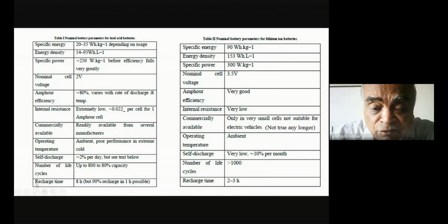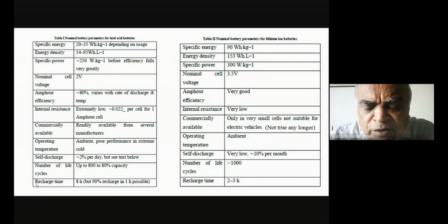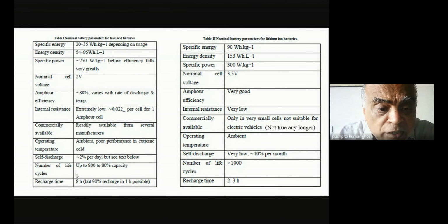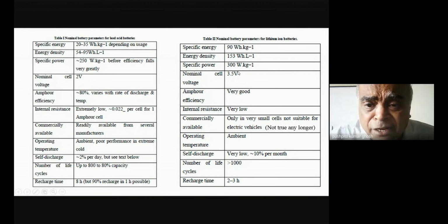And this is very important: if your battery has gone dead, how long will it take you to recharge? Sometimes you are sitting in the airport and your battery has gone dead, there are chargers, but you hardly have 15 minutes of time before you're boarding the flight, and you can't do anything about it. Now, lead-acid battery takes 8 hours to recharge, whereas lithium-ion battery, in a couple of hours, you can more or less get at least some charge. So there are huge advantages, and this is the reason why the lithium-ion battery is increasingly being talked about. But as of today, the lithium-ion battery is certainly much costlier than the lead-acid battery. So that has to be taken into account, and the safety, etc., will need to be also taken into account.